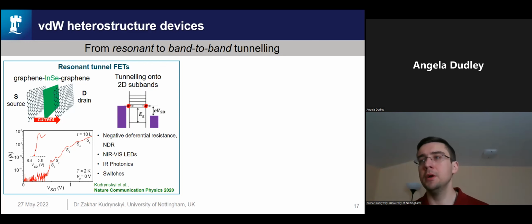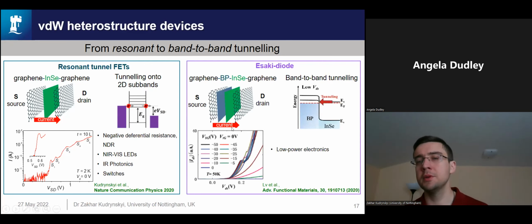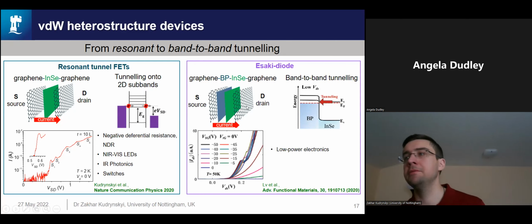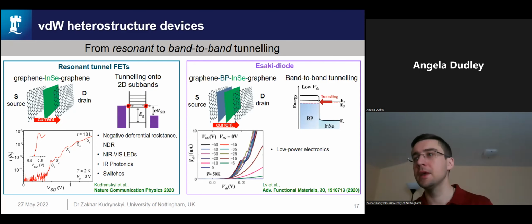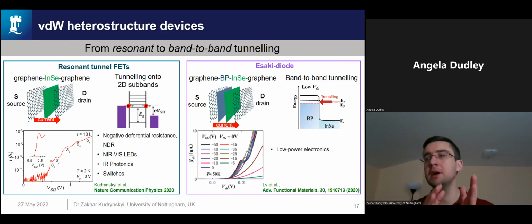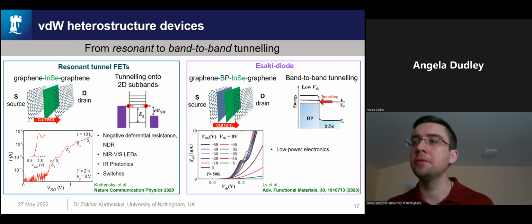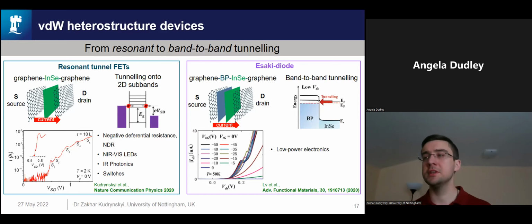We also developed this type of structure, which is a tunnel field effect transistor that combines black phosphorus and indium selenide. In this case, we formed a type 2 interface, a sort of Zener tunneling, and look at band-to-band tunneling across the interface between black phosphorus and indium selenide. And in this case, we observe also negative differential resistance tunable by gate.